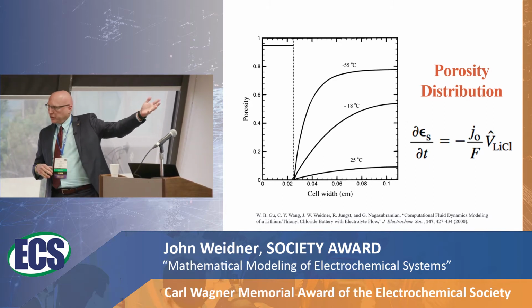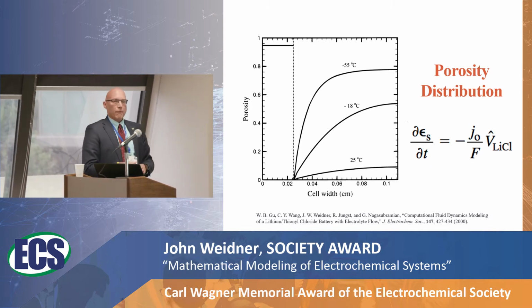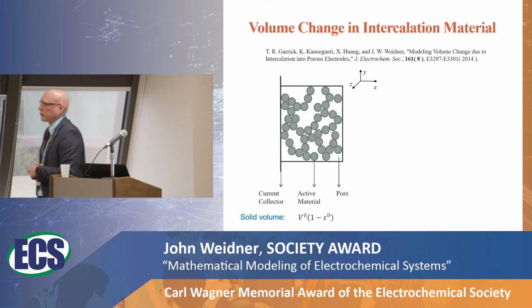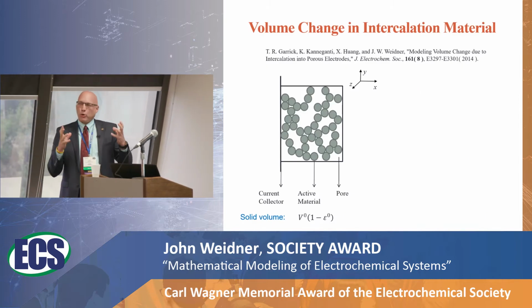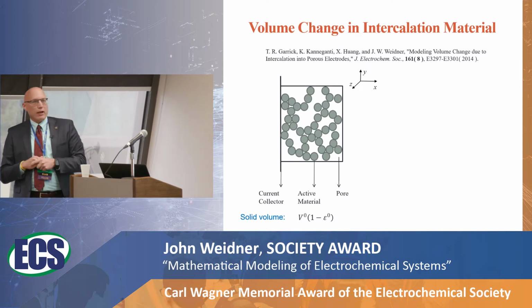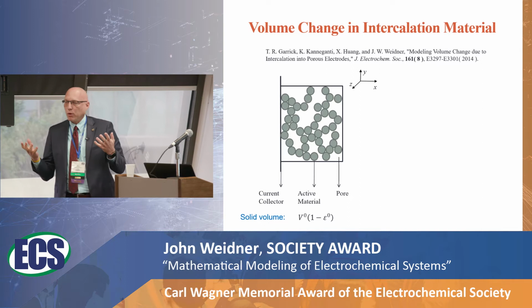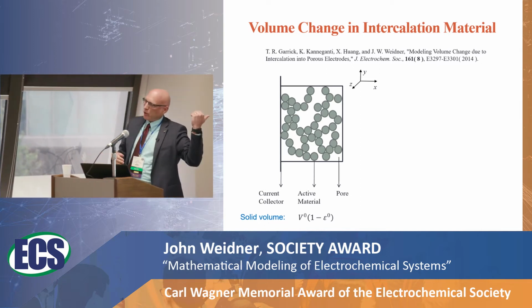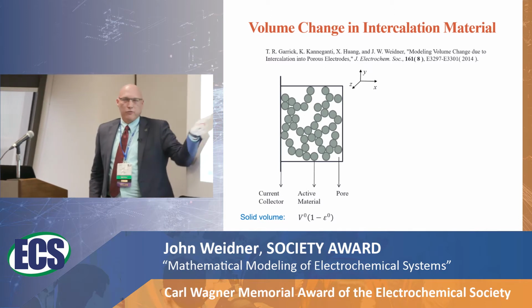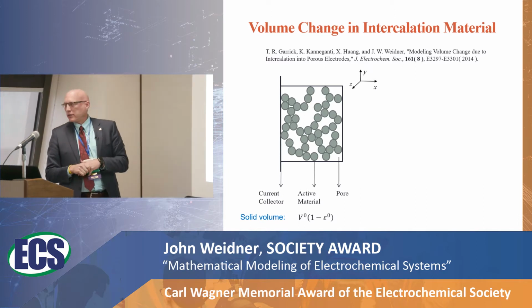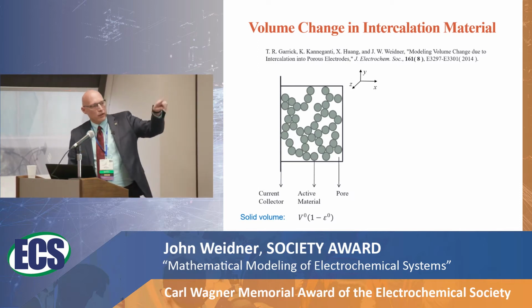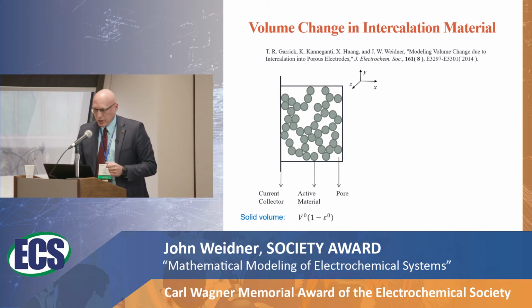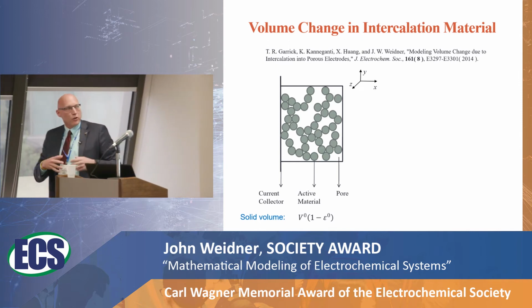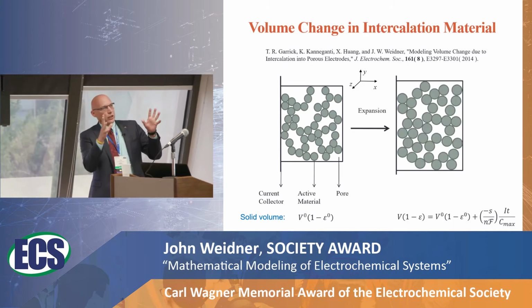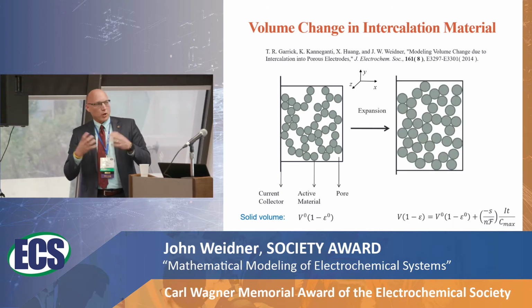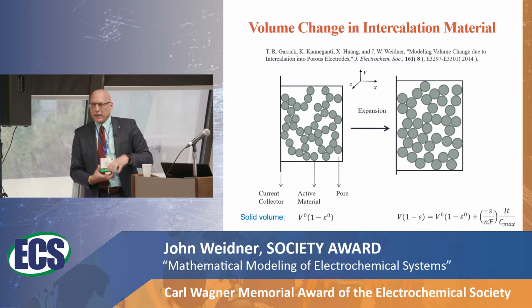Again, what I just showed you in lithium thionyl was depositing material, but here we changed the picture a little bit and made it more like an insertion electrode, and we said, what happens if we have this porous electrode filled with balls, ideally, and we inserted lithium into those balls and they expanded? What would they do? Well, the equation that I showed before would say that if this ball got bigger, it would go into the pores and the porosity would go down, where the volume of the electrode doesn't change. But we know from experiments that volume does expand. I don't know if it's clear from this picture, but those balls got bigger, the porosity got smaller, but also that box grew a little bit.